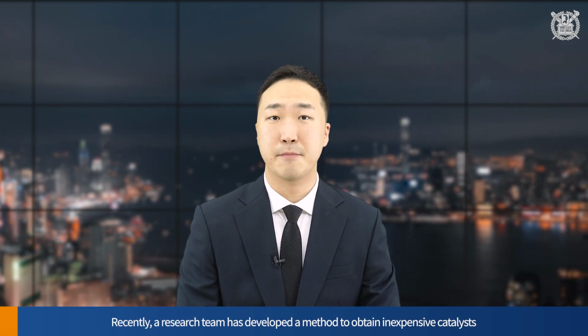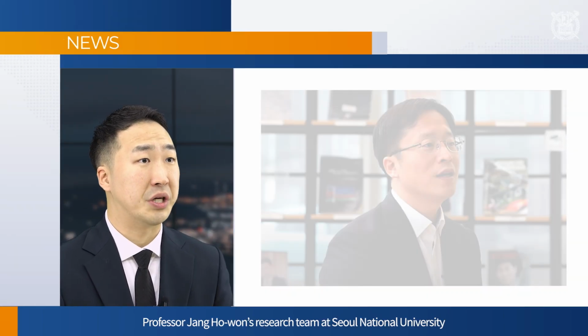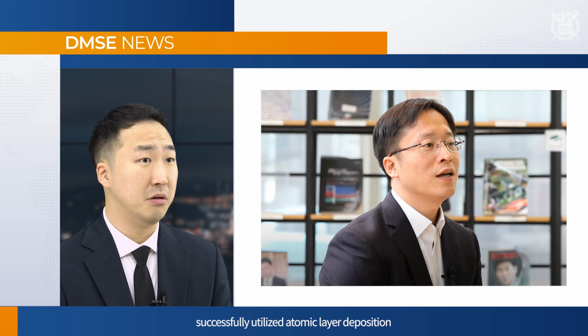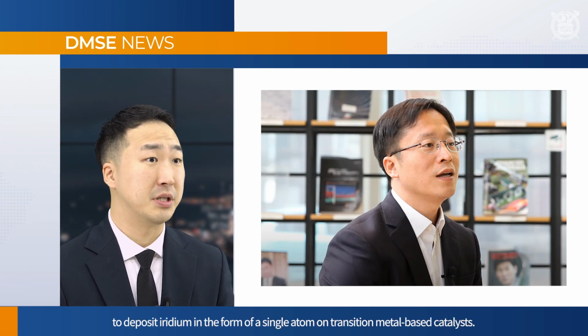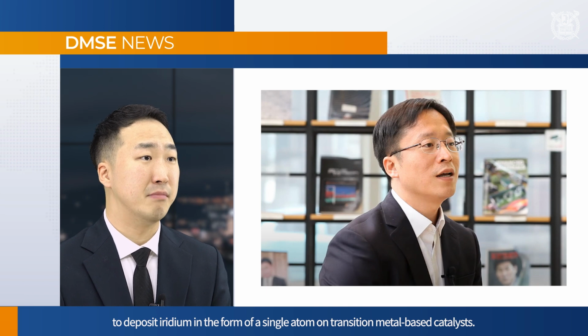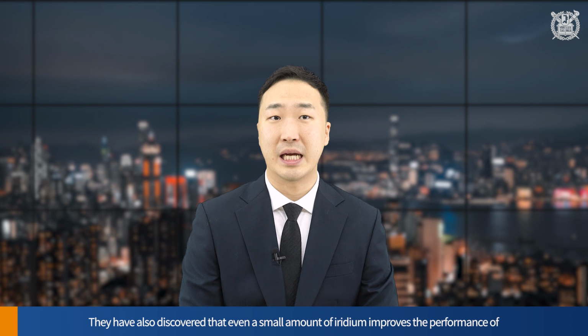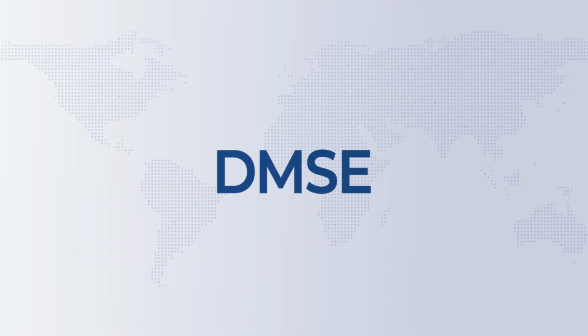Recently, a research team has developed a method to obtain inexpensive catalysts while maximizing the catalytic activity of these transition metal-based catalysts. Professor Jang Ho-won's research team at Seoul National University successfully utilized atomic layer deposition to deposit iridium in the form of a single atom on transition metal-based catalysts. They have also discovered that even a small amount of iridium improves the performance of the photoelectrochemical oxygen evolution reaction of photoelectrodes. As nanoparticles and nanostructures have a very large specific surface area, there has been much research on catalytic reactions in the field of energy.